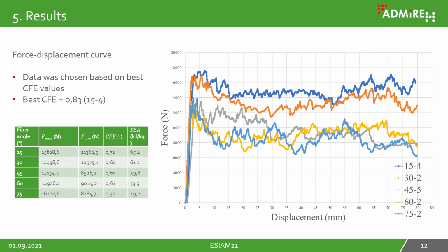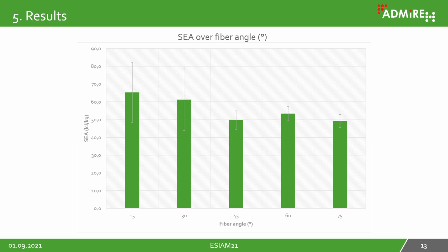That the 15-degree fiber stack-up has the highest specific energy absorption can be explained by the basics of composite materials, where if the loads are applied parallel to the fiber direction, the fiber can absorb less energy compared to a perpendicular fiber angle. This diagram summarizes the specific energy absorption average values obtained for all sets of specimens. It shows that the 15-degree fiber stack-up has the highest specific energy absorption capability. As explained earlier, this is explained by the basics of composite materials.